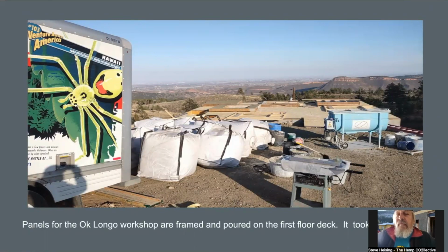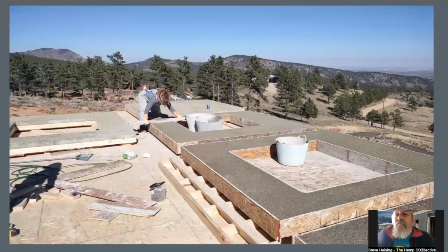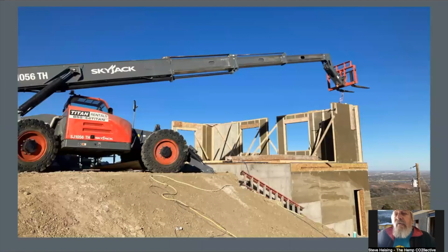And this one, hemp comes in these big super sacks, and you can see a 2-bag mixer sitting back there that broke about 2 weeks into the project. Then we used a regular mortar mixer, and there's forms laid out on the deck, and we're filling them, getting ready to pour them, stand them up. Here we go. We can stick them up with a telehandler, and you don't need a huge crane.